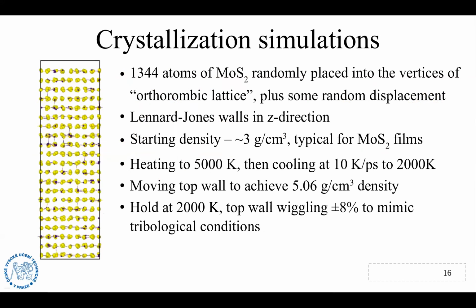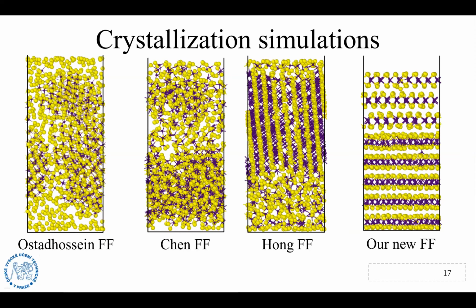So another simulation where I'm trying really hard to crystallize something. Well, a box with atoms. I'm heating it to 5,000 Kelvin to basically randomize the structure. Cool it to 2000 Kelvin, and then I kind of mimic tribological conditions by compressing and expanding the cell, sort of mimicking applying normal load and releasing normal load after the ball has passed the location. So the outcomes, again, new force field, proper 2H MoS2. Other force fields form either this rock salt sodium chloride type MoS or amorphous structures, well, with some resemblance of rock salt MoS.